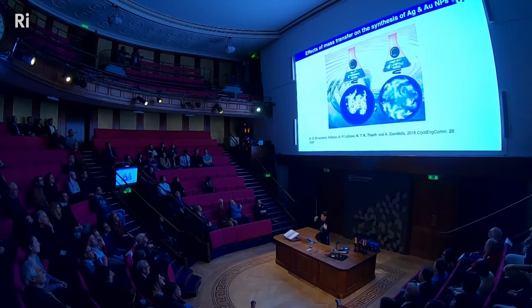And so here you can see that when they aggregate, the nanoparticles all clump together, and overnight it forms these beautiful particles, flowers that I call a red daisy. This image contains a few tens of gold nanoparticles. So as I mentioned at the beginning, the Lycurgus Cup is really rare because you can never reproduce it. But for us, we go to the extreme to look into how we control the reaction. So here I just give you a very quick glimpse of how we're stirring.